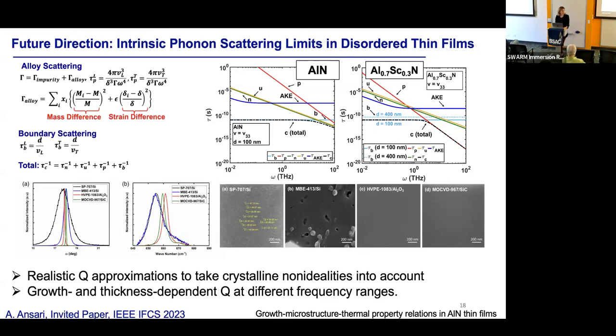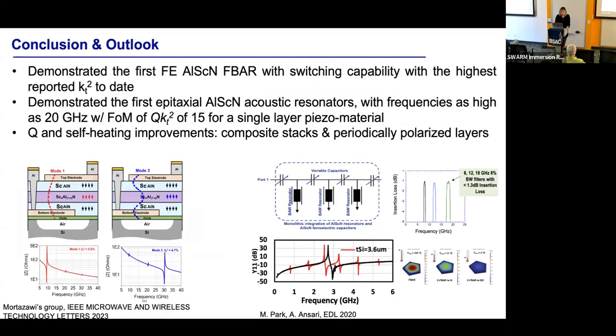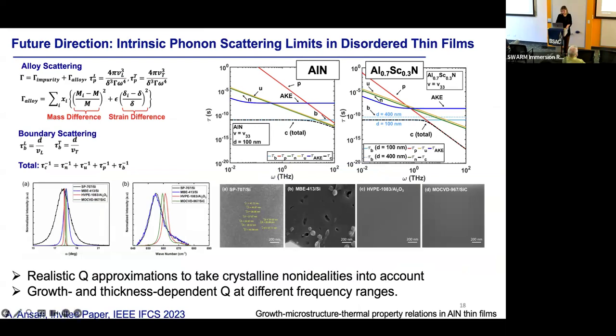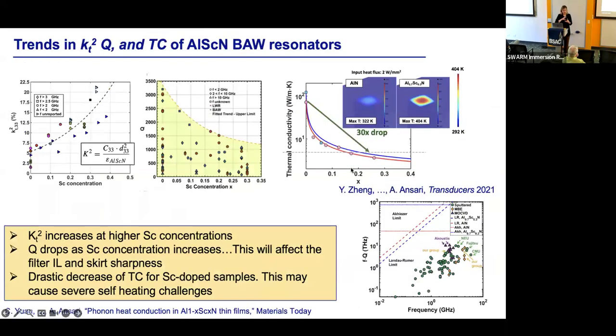Do you also run into more spurious responses when the KT square goes up? We don't, because we use a very simple FBAR structure. So our responses have been pretty clean with more scandium. But something other people have observed is what they call abnormally oriented grains, where the surface isn't as smooth as when you have aluminum nitride. That itself could be another reason why the Qs tend to drop with aluminum scandium nitride.